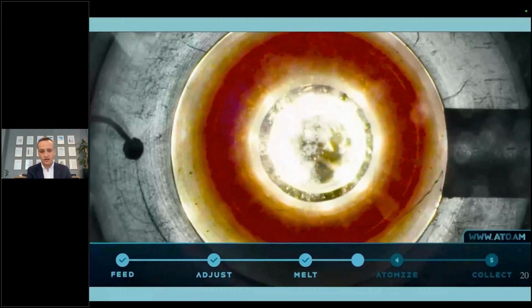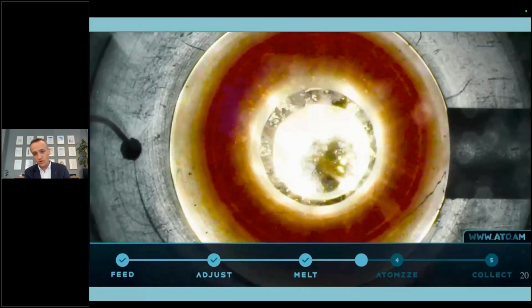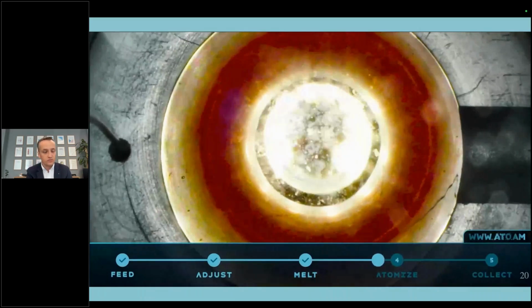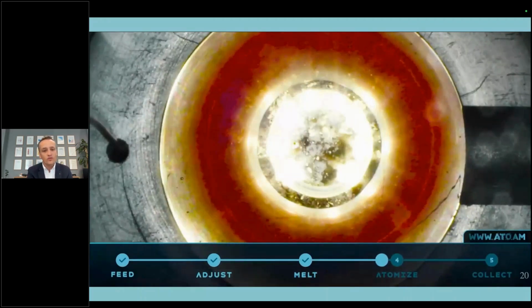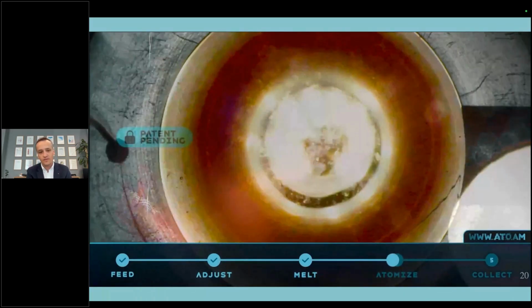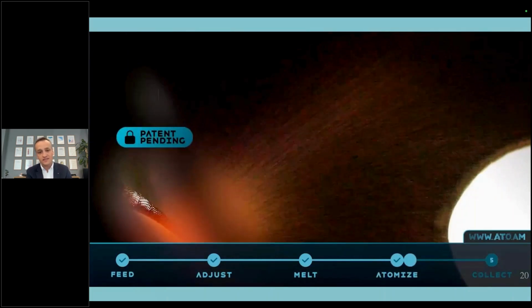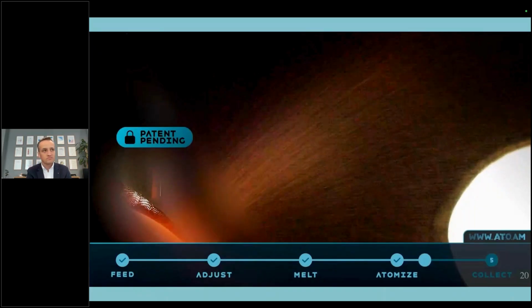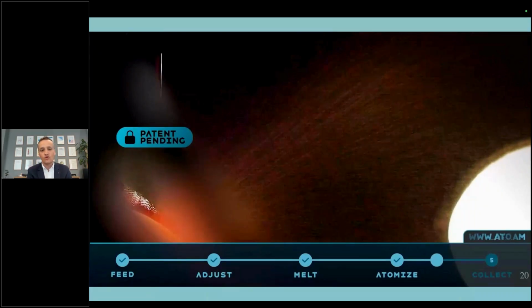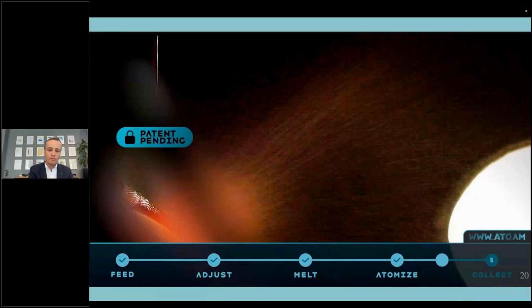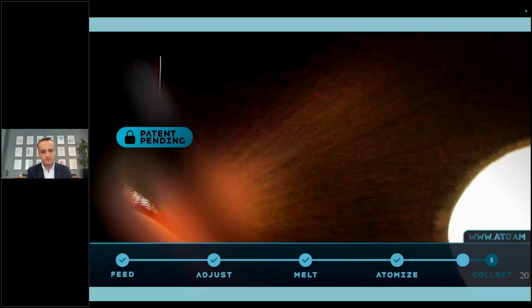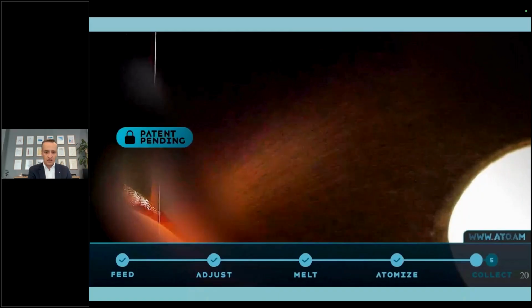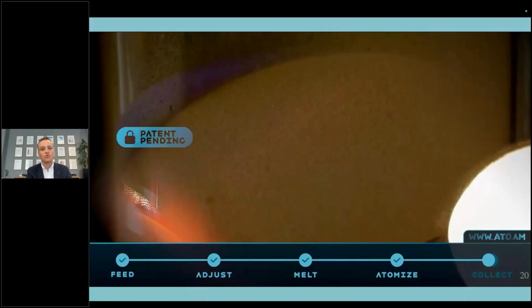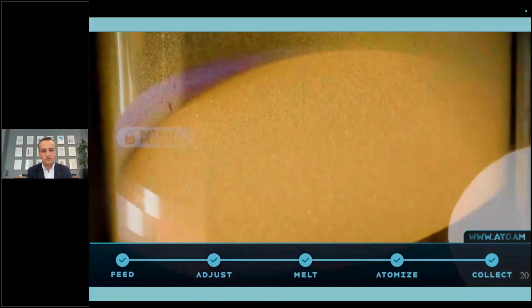When the material is fully liquid, we can release the material from the crucible onto the atomization platform, and then we can achieve an efficiency of the process between 2 to 4 times better compared to the basic module. And of course, after the atomization process, we can collect the powder in our collecting container.